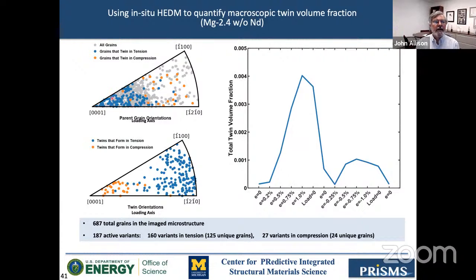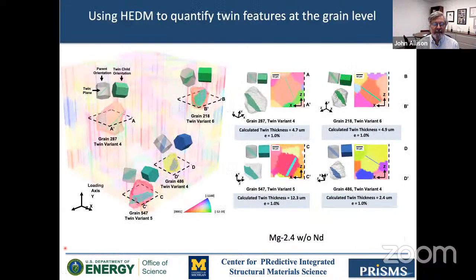So he said, here's the 687 grains total that he imaged. 187 of these twin. 160 in tension and 27 in compression. And so he can tell which particular grains have which particular orientation and so forth. So then he had the cumulative twin volume fraction from all grains. And as I said, here the twin volume fraction is low, which made this a pretty difficult experiment. So kudos to him for completing that. And here's a 3D map of these local twinned grains.